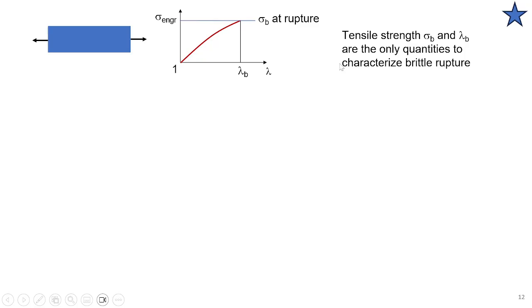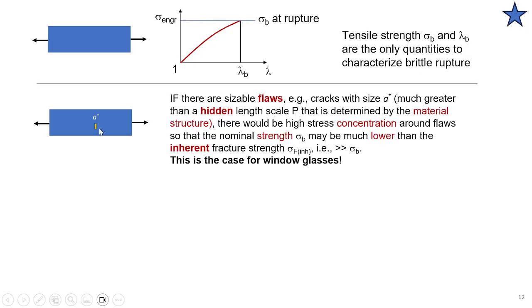So let's take the most remarkable case. When you have a sample that you know that there's no flaw in it, it turns out you just need to describe its tensile strength and how much you can stretch. But that's not how we have thought about rubber for the last 70 years. We thought that rubber is weaker. Remember I said it's weaker by 2 orders of magnitude. One of the things in our mind is it's weaker because there are flaws. But if there are flaws, then indeed it's not sufficient to just characterize your material in terms of stress, and you have to introduce a length scale, okay?